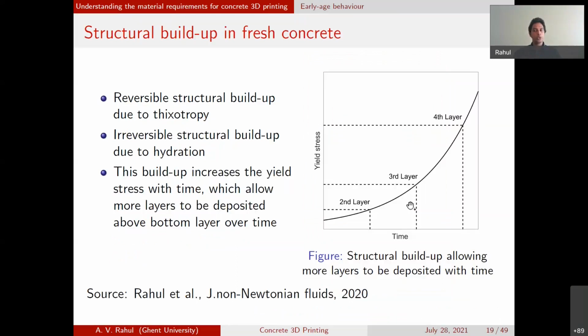One more aspect we need to keep in mind is that both these parameters, the compressive strength or the yield stress, and the elastic modulus, increase with respect to time. This is because there's cement hydration occurring in the material. This causes rigid network connections within the fresh cement paste, within the fresh concrete, and an evolution of these material parameters. So the rate at which you're printing must be in sync with the evolution of these material parameters.